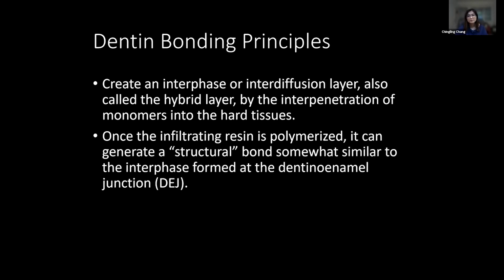The dentin bonding principle is basically to create an interphase or interdiffusion layer, which is called the hybrid layer, as we penetrate the bonding monomer into the hard tissue, into the dentin. So once this infiltration resin is polymerized, it can generate a structure which is very similar to the dentin enamel junction. So it gives a very good strength to bonded restoration on the dentin.